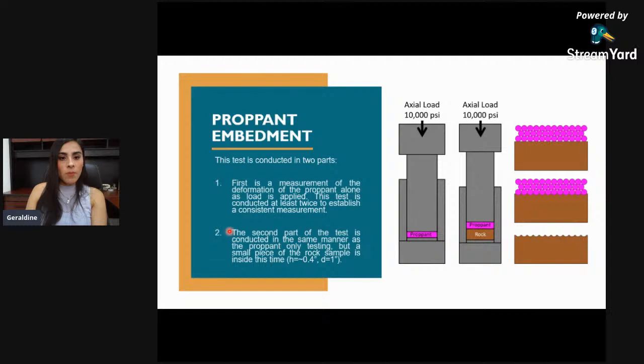So in the second part, you will use the proppant plus the rock. You will put first the rock, you will put the proppant above the sample, and then repeat the same procedure. You apply 10,000 psi of axial load. This is what you will do during the test. You have your sample and your proppant, and what you want to get is how the proppant indents in the sample.